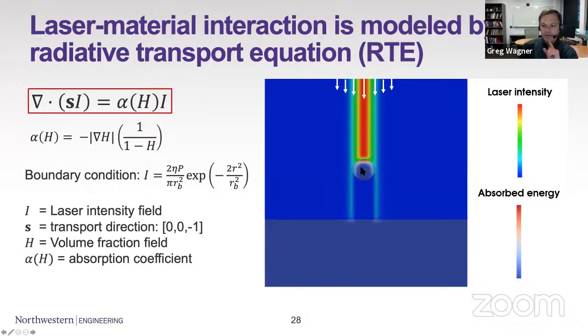We wanted to capture effects like the shadowing of particles, right? So if you have a laser that is incident on a powder particle, you want to capture the fact that the substrate underneath it is going to be shadowed, whether that powder particle is flying through the space above the substrate or is actually sitting on the substrate. So we're solving for a laser intensity field that can be absorbed at the surface of either a powder particle or the substrate. And that gives us this shadowing effect automatically.